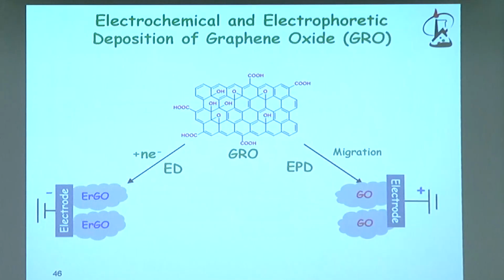So one way of doing that is the electrochemical deposition of graphene oxide. Doron again spoke about the graphene oxide. Graphene oxide can be deposited electrochemically, and we were not the first one to do that, by electrophoretic deposition. In electrophoretic deposition, which is carried out at very high potentials, the graphene oxide is negatively charged, which means that you have to apply positive charge and the graphene oxide will be deposited. But to do it the other way, electrochemically, at relatively mild conditions, is to apply negative potential, which partially, again, reduces the carboxylic acid and other oxygen functionalities on the surface, and because of that, in this case, it will be deposited on the negative electrode.